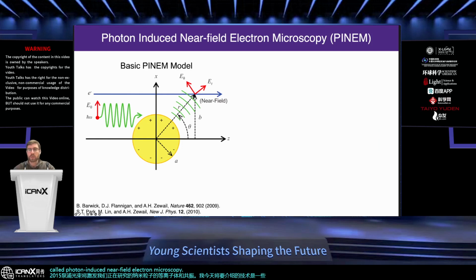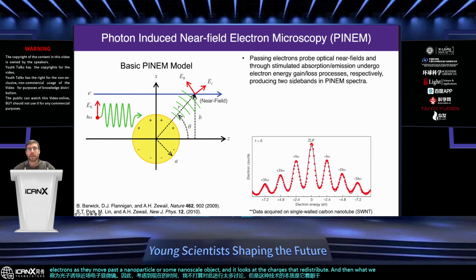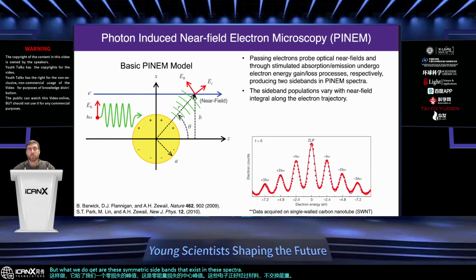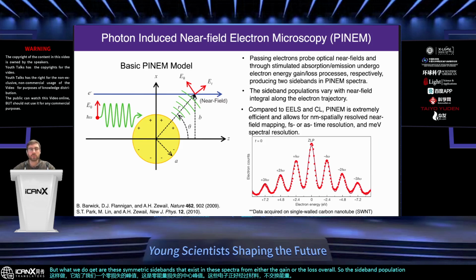Given the time, I'm not going to go too much into this, but what this technique does is look at the electrons as they move past a nanoparticle or some nanoscale object, and look at the charges that redistribute. What we see is that those passing electrons are going to go through either stimulated absorption or emission as they pass through. And so this gives us a zero loss peak. This is the central peak of zero energy loss. These are the electrons that pass right by the material and don't exchange energy. But what we do get are these symmetric sidebands that exist in the spectra from either the gain or the loss overall. So the sideband population is just the integral along the electron trajectory.